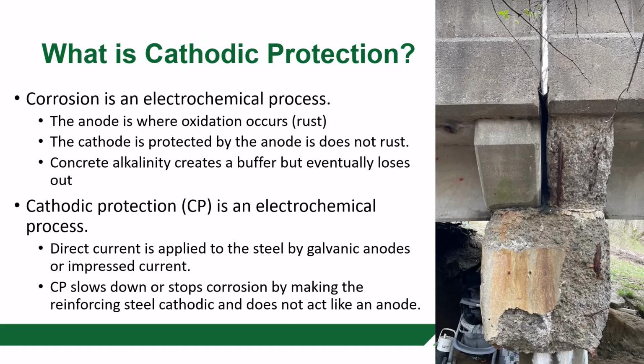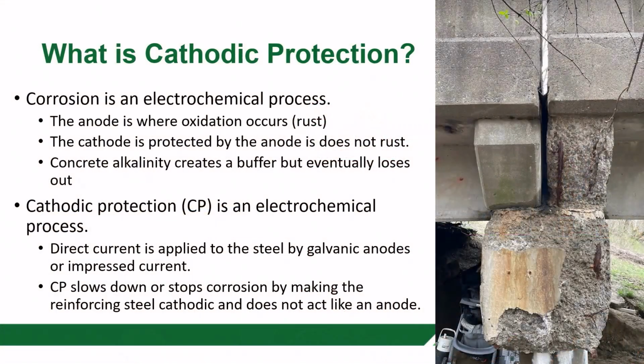Cathodic protection is an electrochemical process. It's basically using the same ideas of the corrosion cell, but using it in a proactive means in order to provide direct current to the reinforcing steel, either by an impressed current system, an outside power supply, or by the use of sacrificial or dissimilar metals, and that's galvanic protection. And once you're trying to make all the reinforcing steel the cathode, or in a non-corroding state, by using these artificial anodes. And so the idea is that you're either going to slow down or stop corrosion with cathodic protection. So it's just another example of a structure, leaking joint, substructure corrosion.